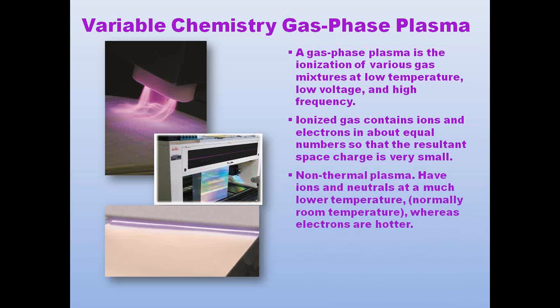These are all non-thermal plasmas. There's a lot of depth and discussion that we can go into further in terms of what these specifically are, but suffice it to say that the species that are contained within this discharge normally will raise the temperature of the treated material no more than about 6 to 10 degrees Fahrenheit. Again, even though the electrons and the electronic discharges are much hotter.